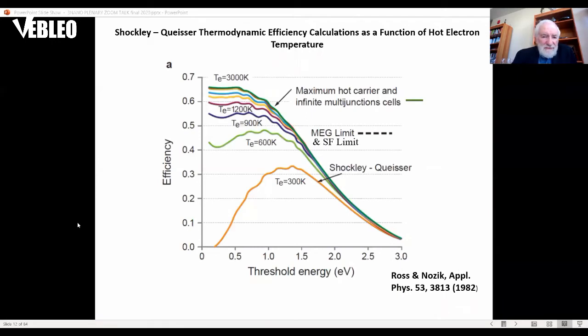So this shows the difference in the efficiency plot compared to the Shockley-Queisser limit. And the Shockley-Queisser limit has this characteristic where at room temperature, 300 K, the maximum efficiency was predicted in 1960 by Shockley-Queisser to be about 32%. But if you could extract all the hot carriers produced at one sun by say using a quantized system, you could double the theoretical efficiency from 32% to about 66%. And that was first published in this paper in 1982.